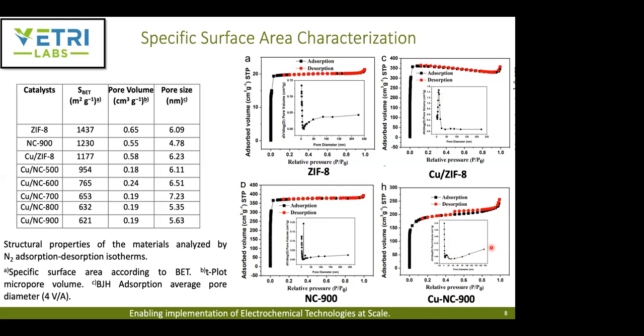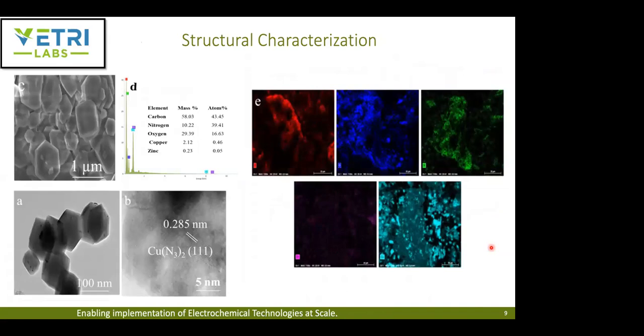Then they did some SEM and TEM analysis to confirm the structure of the obtained ZIF-8. As you can see from the SEM images, it has a well-defined dodecahedral structure with truncated rhomboids, which is a typical ZIF-8 morphology. These findings suggest that the ZIF-8 surface morphology and skeleton structure did not change when they doped with copper nanoparticles. And in the high resolution TEM, you can see lattice fringes with about 0.285 nanometer d-spacing, which belongs to the 111 crystal surface of Cu(N3)2.